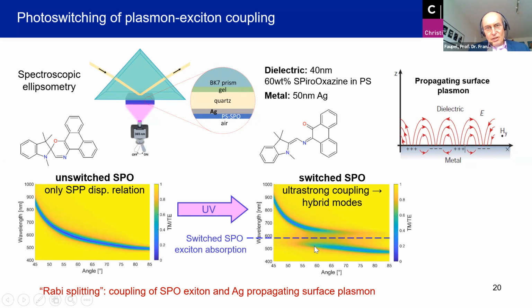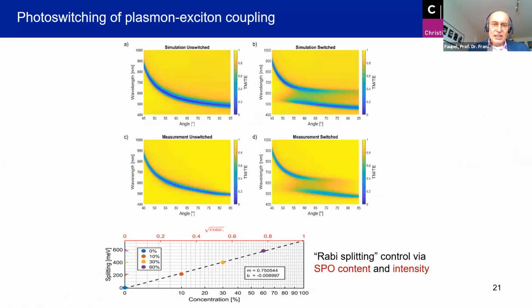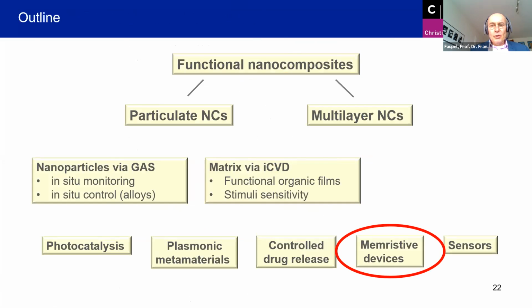We did also theoretical investigations of this process. We got a very good agreement between theory and experiment, and we were able to really demonstrate that this is due to exciton plasmon coupling. And we were also able to tailor the amount of splitting by tailoring the light intensity or the content of these chromophores.